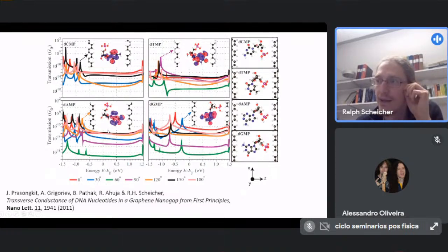And on the x-axis here, this is the energy of the electron relative to the Fermi energy of the graphene electrons, basically. So below the Fermi energy or above the Fermi energy. And basically these peaks correspond to where you get high transmission, and this is typically where you have a good coupling to the molecular orbitals of the nucleobases. So the coupling has to be good, the energy has to have the right value, and then you get some large peaks. So this is on a logarithmic scale here, so you really have very large peaks for certain energies.